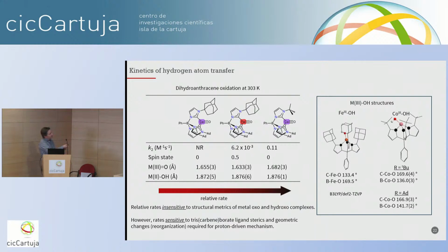So if we look at, since it's a proton-driven hydrogen atom transfer reaction, the structure of the iron hydroxide, which would be the first thing formed from proton transfer, it is slightly bent here, whereas the cobalt hydroxide is very bent. It's almost a sawhorse geometry at cobalt, whereas this is closer. And so our thinking is that the rate here is influenced by the reorganization energy that's required to get to this intermediate species, which is much less for iron than for cobalt. This certainly would make this more sensitive to steric effects. Again, this is something we're still investigating.